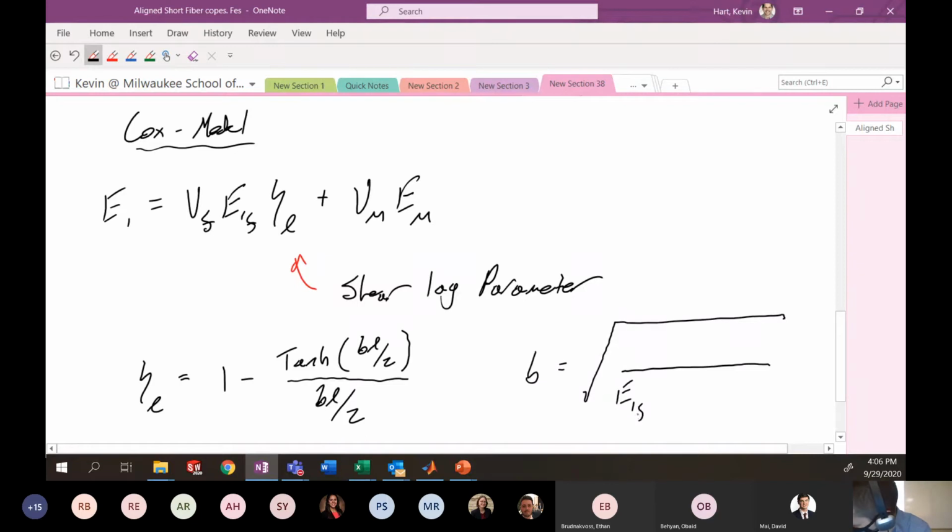It involves modulus in one direction of the fibers, multiplied by the radius of the fiber squared, times the natural log of the radius of the matrix over the radius of the fiber. Remember, these are terms that we defined with that little model that we had. Those terms are generally related to the volume fraction. And the numerator here is 2GM. So this is your full Cox model.